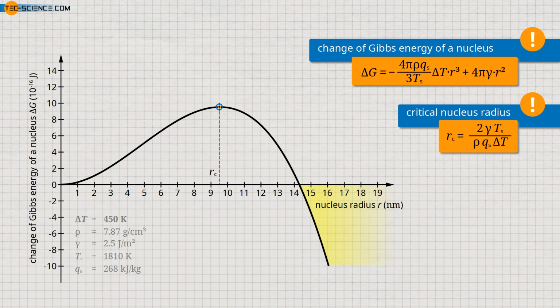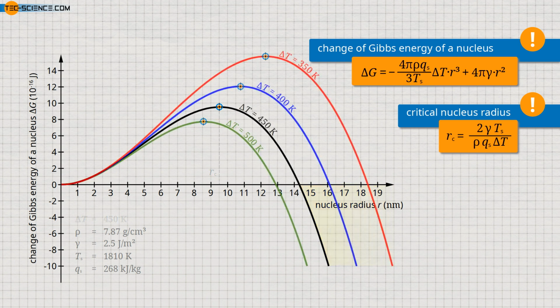However, the probability that such a large nucleus is formed is low due to the large number of atoms required for this. According to the formula derived, supercooling obviously has a decisive influence on the critical nucleation radius. The greater the supercooling, the smaller the critical nucleus radius. At the same time, as the critical nucleation radius decreases, the activation energy also decreases. Thus, with increasing supercooling, it becomes more and more likely that nuclei capable of growth will form.